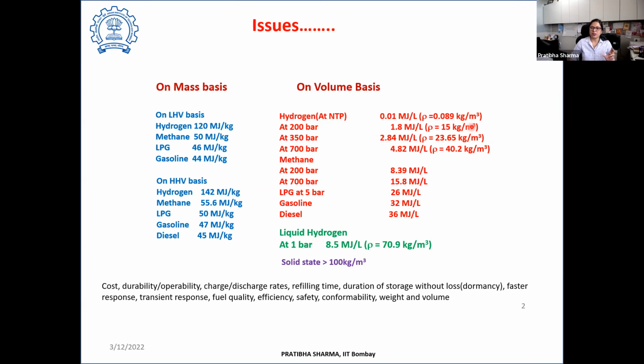Now, if you still want to make it conformable or reduce the volume of the container, what you have to do is increase the pressure. If we increase the pressure, let us say to 200 bar, the energy density improves from 0.01 to 1.8 megajoule per liter. If we further increase pressure, say to 350 bar, then it is 2.84 megajoule per liter. And it keeps on increasing as we increase the pressure.